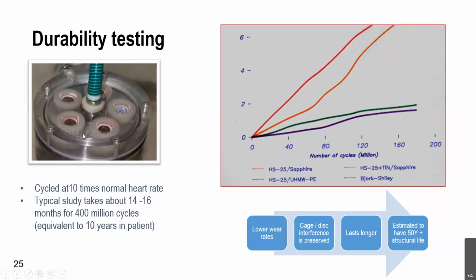The device is tested in a particular system called an accelerated durability tester. The entire system has to be designed and developed here. And the valves are cycled at 10 times the normal heart rate. And it takes typically about 14 to 16 months of continuous testing to reach this 400 million cycles.